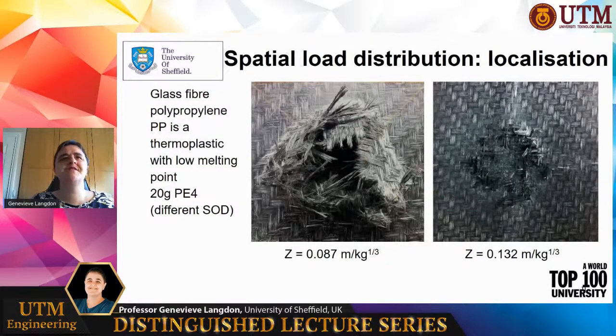Fiber-reinforced composites are also very sensitive to load distribution. A highly localized load will produce a very localized rupture, a hole through the center of the panel. And this is showing now our glass fiber polypropylene, which is a thermoplastic. So with a thermoplastic, which has a lower melting point than, say, epoxy, you see more damage to the resin occurring as well. If you look at the two images on your screen, both of them have been tested at the same charge mass, 20 grams, but they have different standoff distances, which is the distance between the explosive charge and the target face itself.